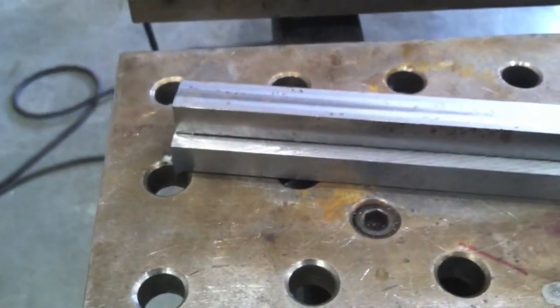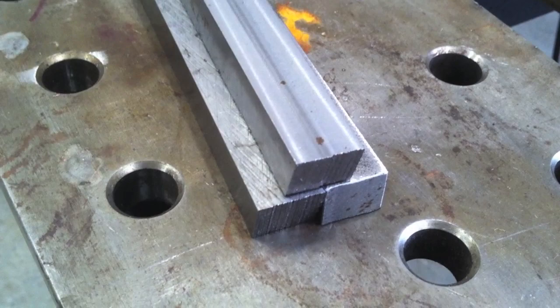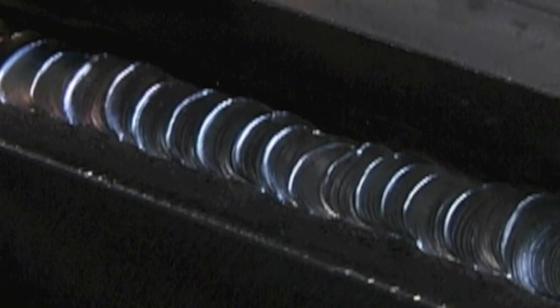We're doing some 4140 here now, some half-inch or so thick scrap bar stock. We're gonna do some heavy lap joints now in 4140. 4140 is like chromoly except it's got more carbon content and it is used extensively in fixturing because of its strength and hardness and mainly its dimensional stability. Cold rolled is a lot cheaper but it's also a problem because it warps. You start machining on it to get flat faces and it moves around because there's stresses build up in it. So 4140 is a lot more stable dimensionally speaking when you start machining things after welding.